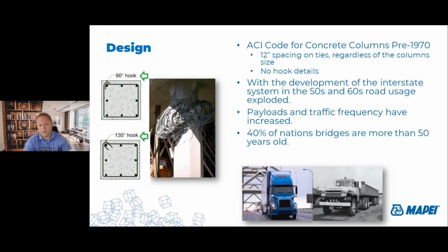So the design community took a step back and said, how can we do this better? Now the spacing and the size of the ties is dependent on the column size and on the longitudinal bars. More importantly, they require a 135-degree hook, so that if you have a significant loading event, the concrete puts the tails of that hook in compression and keeps it from opening up. That was a learning lesson, but there are still a lot of columns from before the 1970s that have this issue.